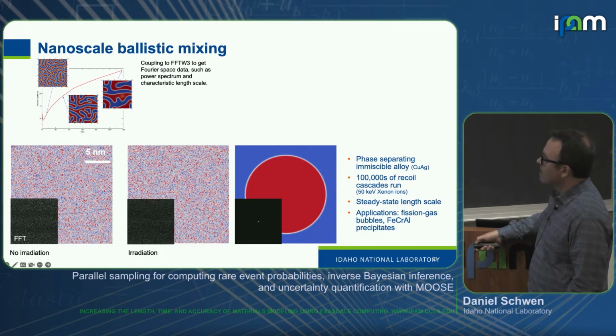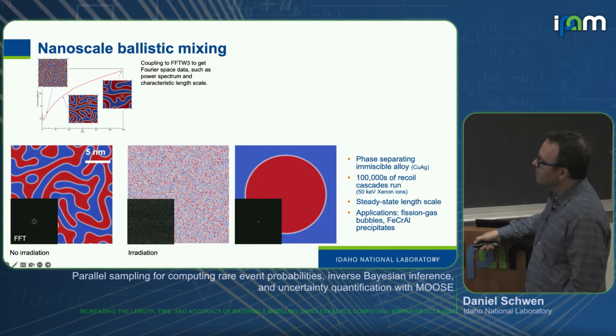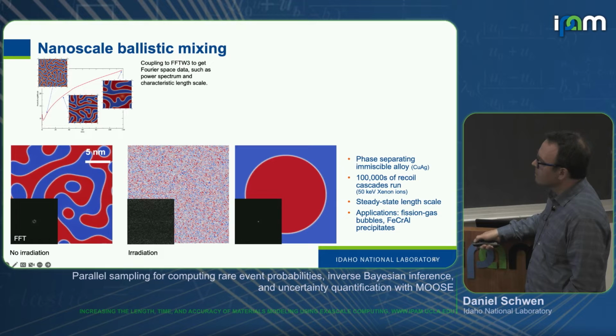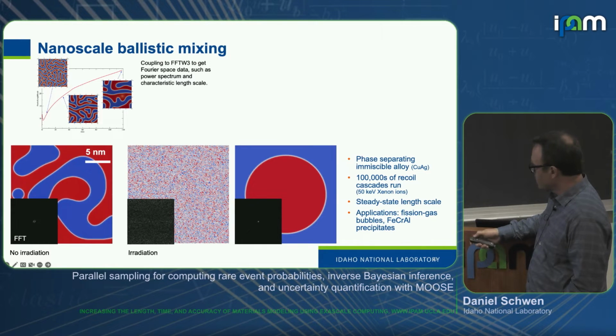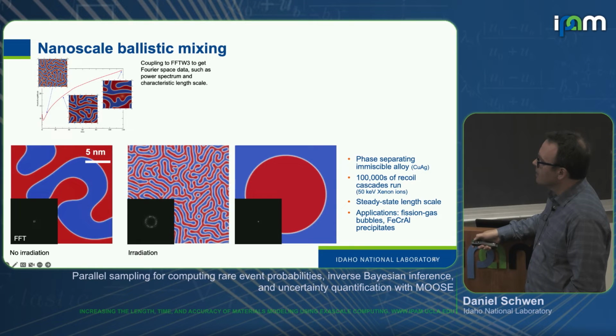So what we're seeing here is an immiscible model alloy, like an AB alloy, could be copper silver, for example, right? If we just heat this up, it'll simply phase separate, right? So just a spinodal decomposition here. That's the simulated FFT, which is also like a built-in capability.